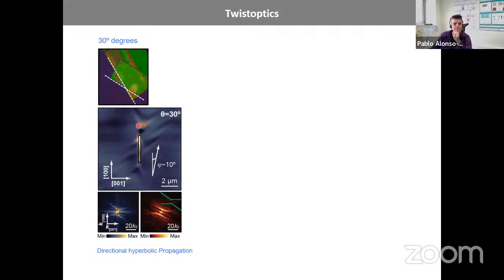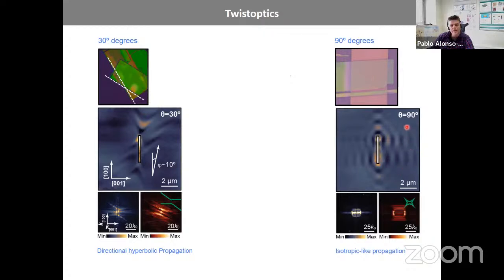And then here you can see that the propagation is still hyperbolic, but it's slightly tilted. The hyperbola is not symmetric, and it's slightly tilted because of this. But still it's hyperbolic. If we put the two flakes at 90 degrees, just like this, we observe the following: we now have propagation of polaritons along all directions. So we're recovering the isotropic case. We have kind of a circle, more like a square, and we have propagation along all directions, like isotropic.